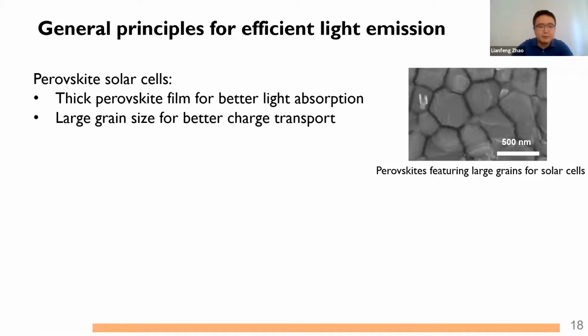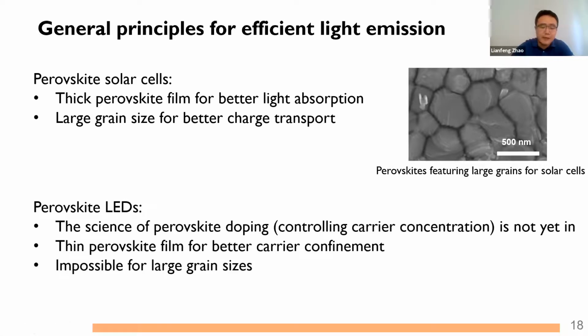So it is well known that for an efficient perovskite solar cell, we need a relatively thick perovskite thin film for better light absorption, and we want to keep the grain size big for better charge transport. But for LEDs, the principles are a bit different. Right now, there's no efficient doping strategy for perovskite yet. So in other words, there are no p-n junctions for LEDs, unlike the case for inorganic semiconductor-based LEDs. In this case, we have to keep the perovskite film very thin for better carrier confinement.